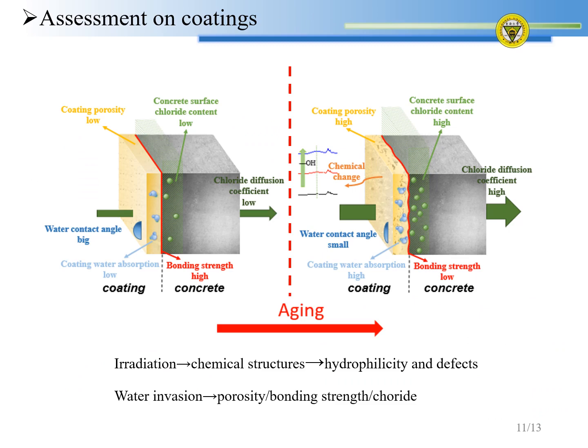So far, combining the degradation and protection of coating, we obtained an evaluation system. Look at the picture. The increase in both hydrophilicity and the defects on the coating surface is related to the change of chemical structures, and it is caused by ultraviolet irradiation. The pores and free volume increase, so the water absorption increases, and the invasion of water keeps weakening the interface and reduces the resistance to chloride.